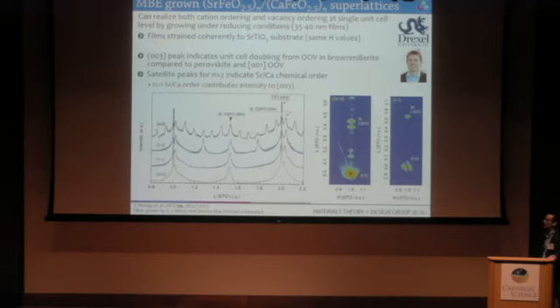And so what was done is that these films were grown by oxide molecular beam epitaxy by Steve May's group, and what we should expect is this type of orientation for the oxygen vacancies. Steve May's group at Drexel grew these on strontium titanate substrates. They're coherently strained, 35 to 40 nanometer films. He also looked at different periodicities of those superlattices. So in addition to the 1-1 that I just described to you, he looked at a 2-2 and a 6-6 period superlattice. These are 00L truncation rods taken at the APS.